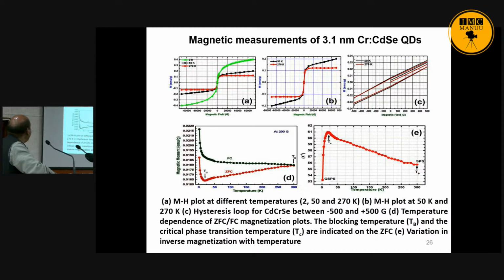Then this is an MH curve, magnetization versus magnetic field. You can see that we are also able to get the hysteresis here. We are getting hysteresis at room temperature, so this is the confirmation. It is showing that this is a room temperature ferromagnetic chromium doped CdSe quantum dot. So this is the observation.